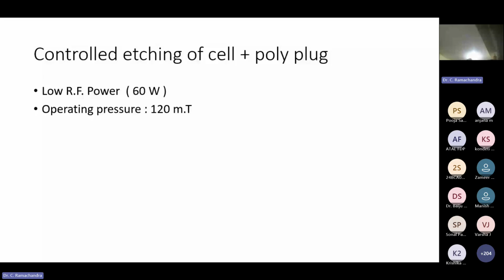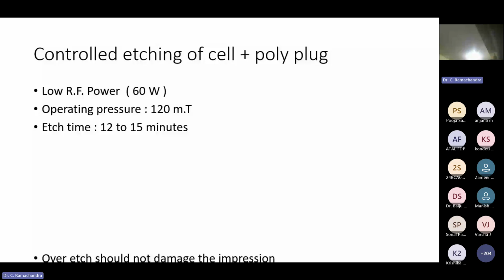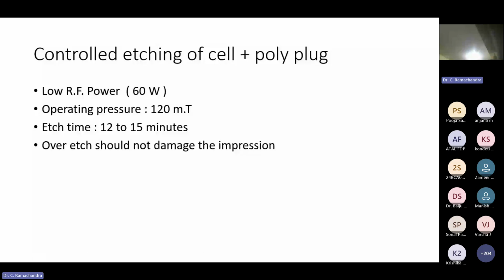Then operating pressure, I did some calculation for the chamber and worked out around 100 to 120 millitorr. Then etch time cannot be too large, again for industry purposes. So somewhere 12 to 15 minutes was acceptable. And overetch is also a problem, it will damage the impression. So I need to make sure that it is not overetching the polyplug.